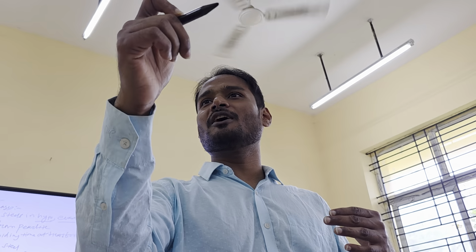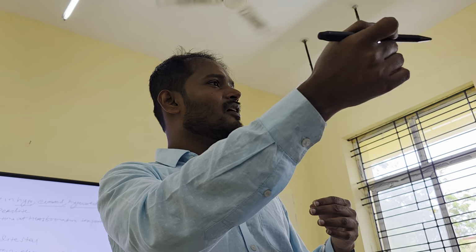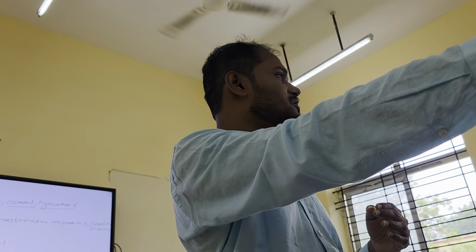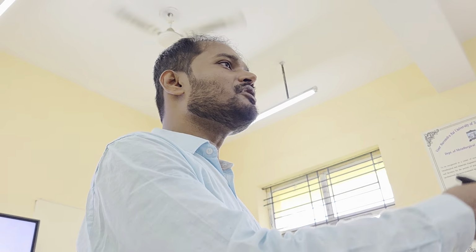Because the moment it moves, the cementite will come and it will stop. Suppose it crosses over, it will suddenly interact with the cementite, so it cannot move. So strength will be more, because strength depends upon dislocation motion. If dislocation is moving easily, it is ductile. If dislocation movement is hindered and very slow, it is stronger or harder.